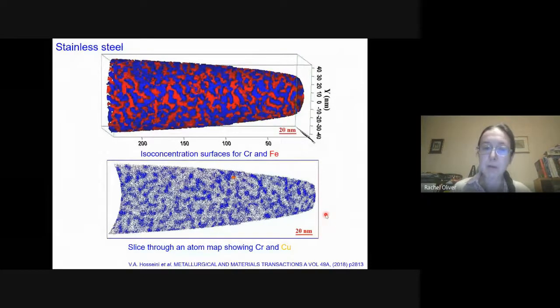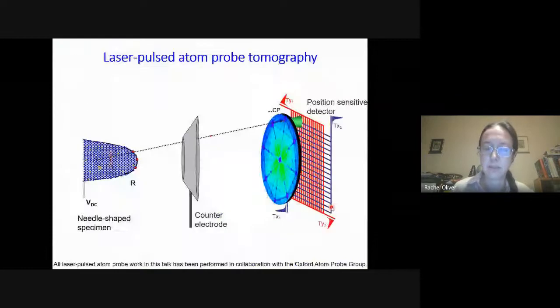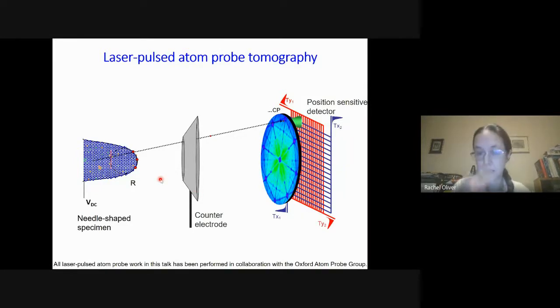We can map out the composition in 3D and find this nanoscale phase separation that we've been talking about. So how do we do this on semiconductors rather than metals? Well, with semiconductors, it turns out to be pretty difficult to get these very fast voltage pulses, which are used to cause field evaporation in the metals. The conductivity is just a bit low.